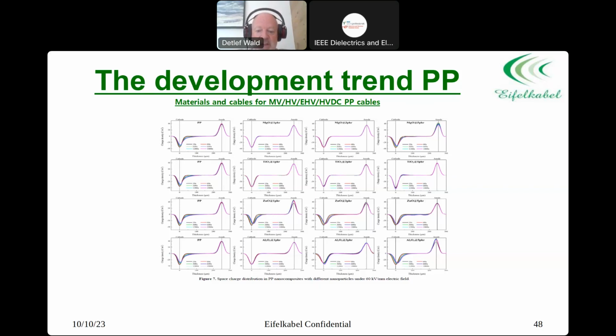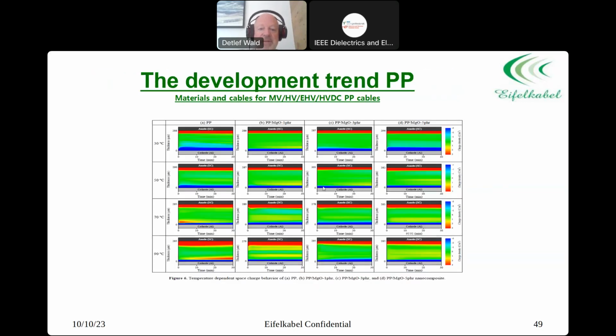The space charge was measured at 60 kilovolt, and it was done as a nanocomposite, showing the differences of different additives to the space charge development compared to virgin polypropylene. Same thing here. I think it's easier to see because it just shows the space charge development. Comparing to this, here again, it shows it at different temperatures and how the space charges are developed over time at different temperatures in the same conditions that were described before. So it shows also, depending which additive you are adding, you either can suppress space charges, or with a higher addition, you actually add space charge.